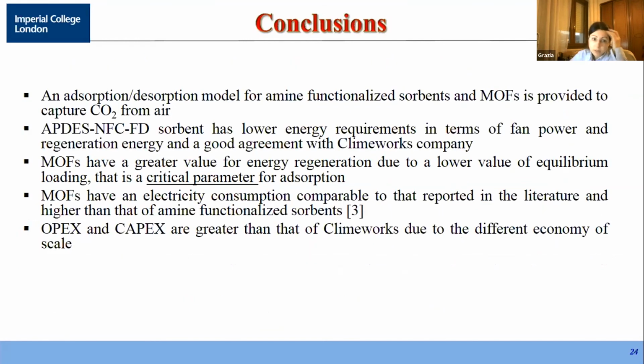In conclusion, we developed a model for adsorption and desorption for amine-functionalized sorbent and metal organic frameworks, and we found that the cellulose-based sorbent has lower energy requirements in terms of fan power and energy for regeneration, and there is good agreement with the Climeworks company.